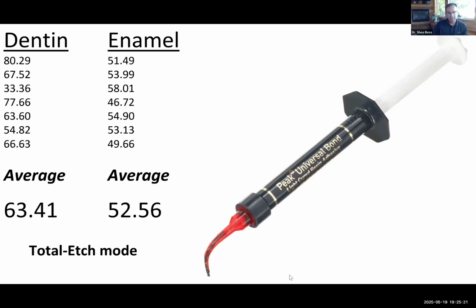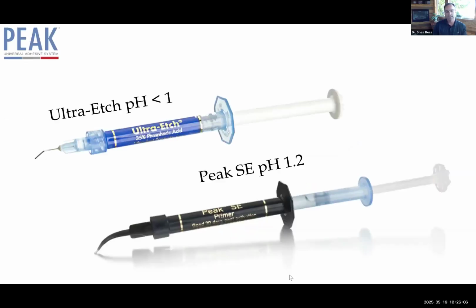and this is my average. If I use total etch, 35% phosphoric acid, this is the highest bond strengths I got to enamel than any other adhesive out there. So to me, in my office, if I'm trying to bond a mandibular incisor and I'm extremely concerned about bond strengths, guess which adhesive I'm going to use? Am I going to use a G-Bond, which is going to give me in the 20 range? Am I going to use a Scotch Bond that's going to give me in the 25, 26 range? Or am I going to use Peak Universal Bond that's going to give me 52, which is significantly higher, and is going to increase the chance of me being successful and keeping my restorations in place.